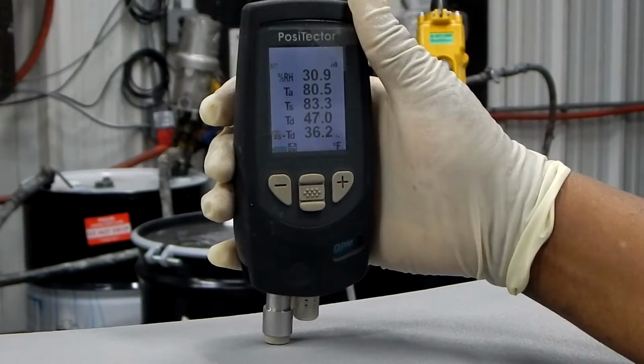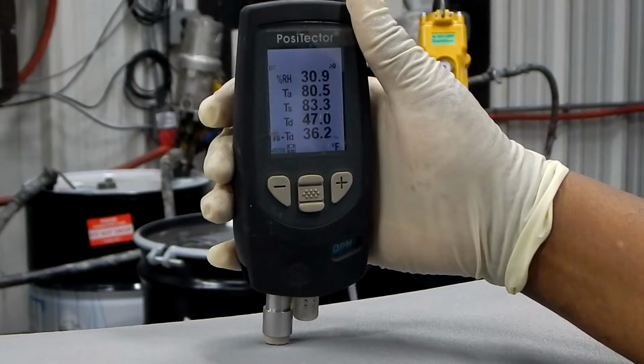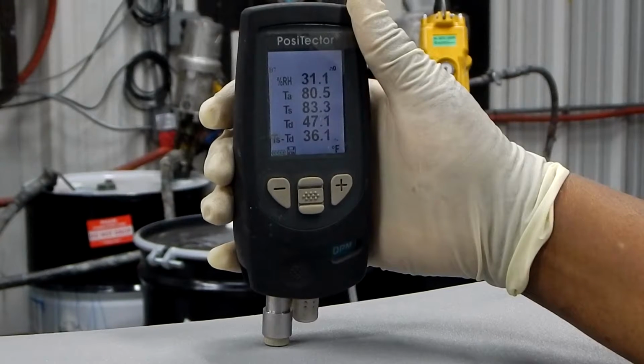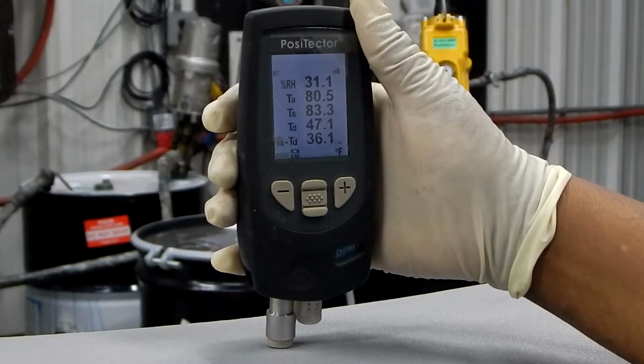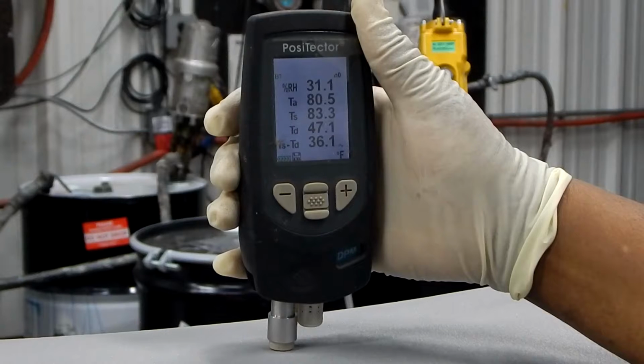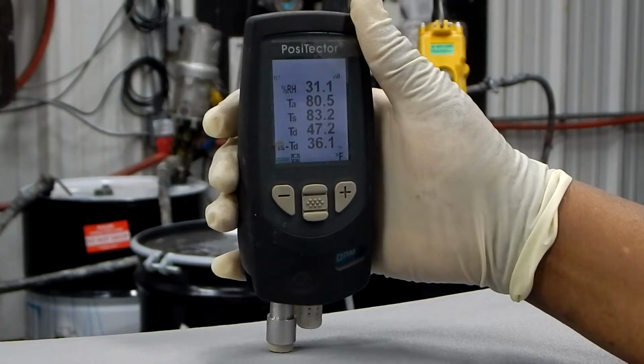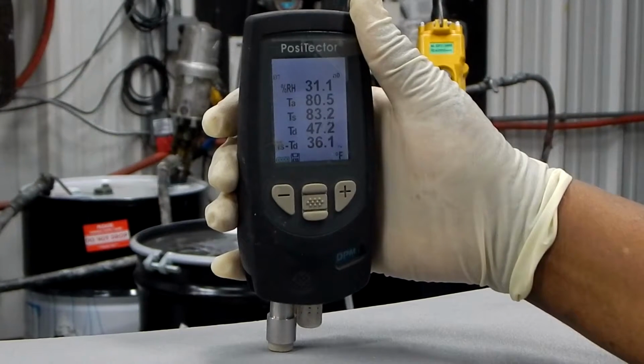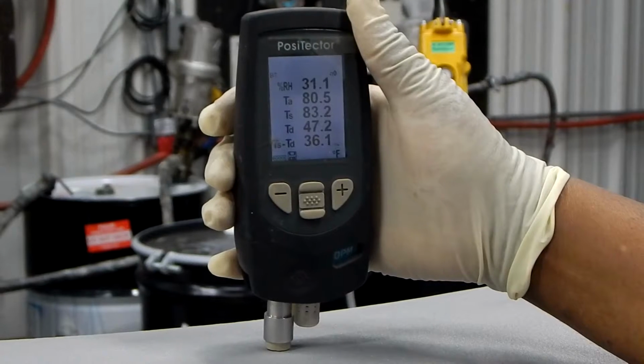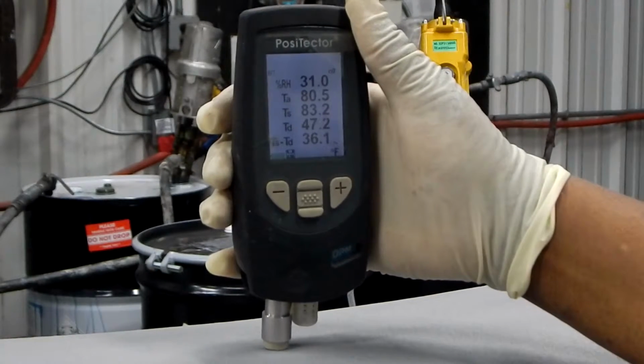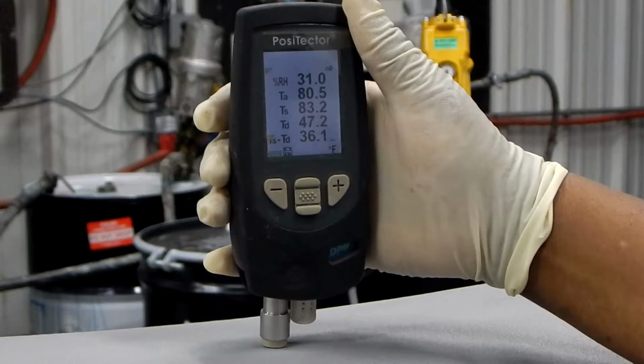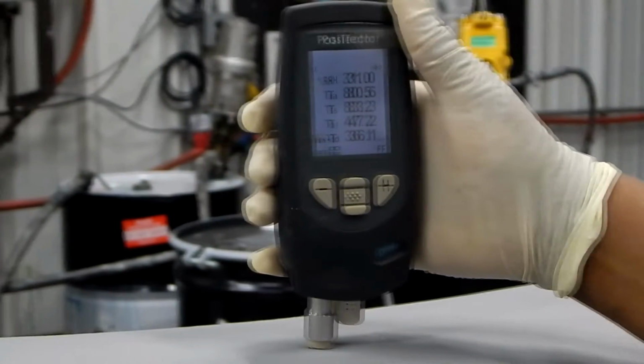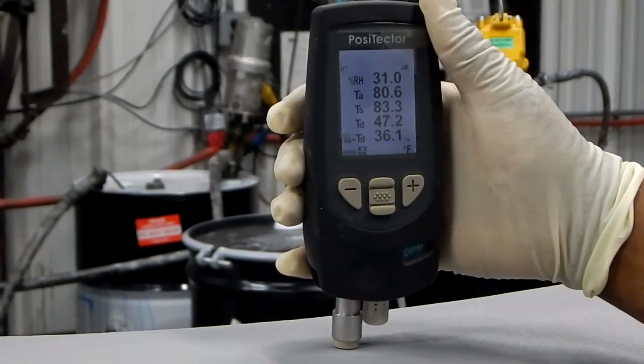Step 11. Verify surface temperature at coating. The surface temperature at coating is the temperature of the surface to be coated. If the fitting is too hot or cold, the coating will not properly attach itself to the fitting. The following steps are needed. View the TS reading. Verify that the temperature is greater than 50 degrees and 5 degrees above the dew point, to a maximum of 212 degrees. Record in the daily inspection log.